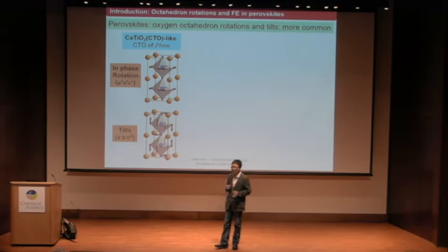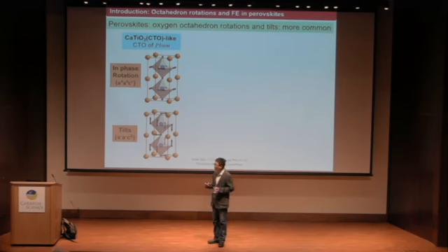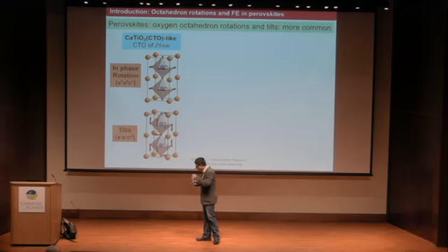We have patterns of octahedral rotations. For example, in general, you can have a rotation around the 110 direction, and you can have another rotation around the 001 direction. For the 001 direction, for simplicity, we often call it rotation, and for the 110 direction rotation, we call it tilt.